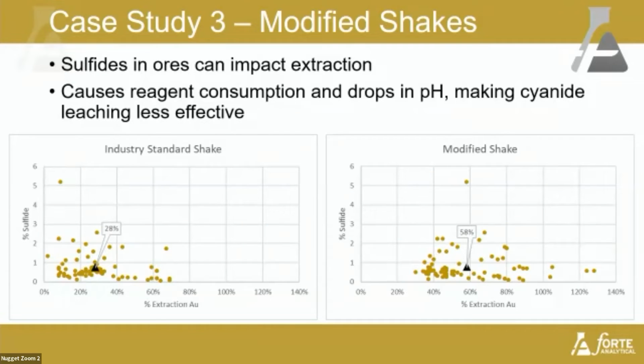So what we did is we ran the same exact samples in duplicate, but we monitored pH throughout before adding cyanide and continued adding lime until the pH stabilized at 10.5 over time. Once it stabilized, we added our cyanide to the solution and we ended up with a higher recovery of 58% on average. So this is a good demonstration of knowing your ore and how to actually run the test. When you get the test numbers, what do you do with them?